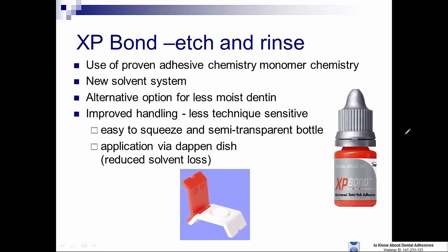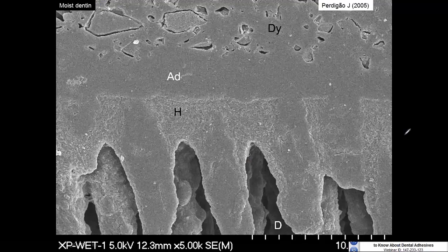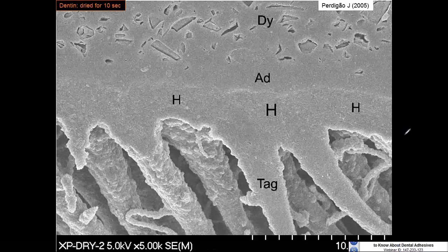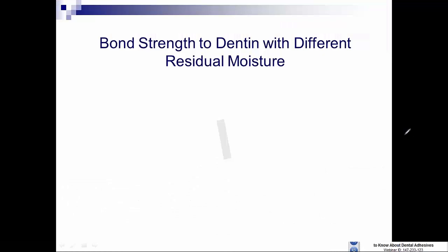Now, there is an etch and rinse adhesive system that seems to be very insensitive to collapsed collagen. It is called XP Bond. It contains a very interesting solvent, tertiary butanol. Here we see the same micrograph, the H listing the hybrid layer, showing full and complete interpenetration of resin monomers in moist dentin and in dry dentin. But this is the only etch and rinse adhesive system available that is known to resist the collapsed collagen. And in fact, when we do static bond testing, we see that XP Bond is relatively insensitive in terms of its bond strengths for dentin that is overdried or overwet, compared to other ethanol-containing adhesive systems whose bond strengths are significantly reduced by overdrying or by having too much water in the cavity preparation.